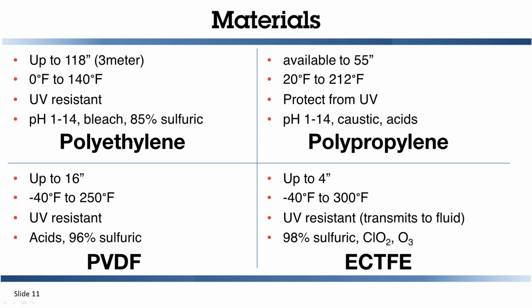Polypropylene is available up to 55 inch, with a temperature range of 20F to 212F. It is not UV resistant, so you have to protect it from the sun, whether with an awning covering the system or by painting it with latex-based paint. Again, a pH range of 1 to 14. Typical applications are caustics and acids.